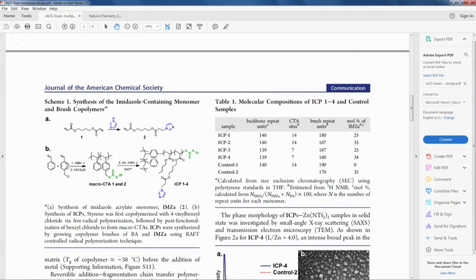You can take this component in a certain ratio, so that you can control the amount of CH2Cl that is there, and then you are using this reagent in order to replace this Cl with this particular moiety, and you can immediately recognize that this becomes a chain transfer agent as per our discussion before. This is a thiocarbonyl thio moiety, basically a trithiocarbonate moiety. This can also be a chain transfer agent, you can have 2 sulfurs or 3 sulfurs together.